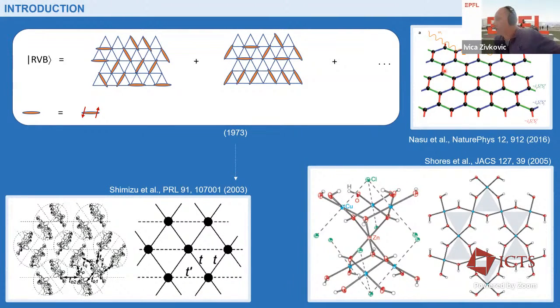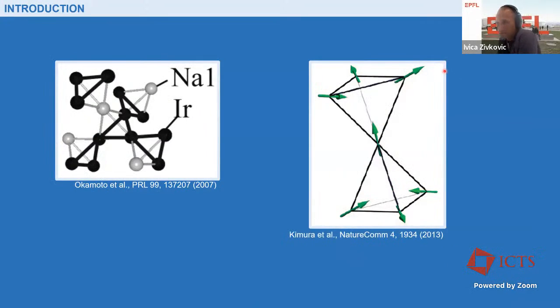Now, research is still going on, and there are still problems of establishing, from the materials point of view, good materials which actually realize the Kitaev model without other problems. For instance, in ruthenium trichloride, there was a problem of stacking faults. And then there is always a question of the presence of normal Heisenberg interactions, which move the materials away from the ideal case of Kitaev interactions. In 3D, it's not much better, I would say.